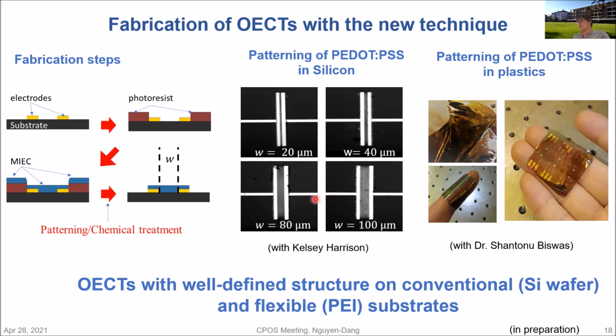It also works with plastic substrates. For example, thanks to the recommendation of Dr. Shantonu Biswas, I worked with PEI substrates. It's really interesting that we can put the gold on the silicon, go through the whole fabrication steps without destroying the substrate, and then just peel off the substrate, and on it the PEDOT:PSS is patterned in the very same way as you pattern PEDOT:PSS on silicon.